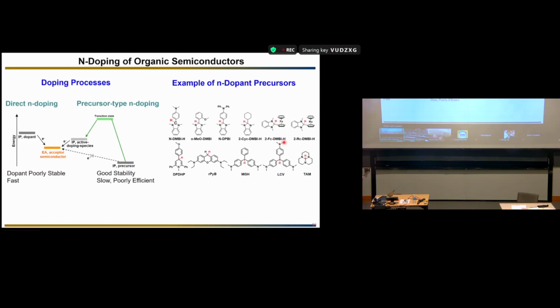But what you do is some chemistry on this molecule to convert it to a species which can then donate the electron. So this process is energetically demanding. So you have a problem of the doping itself, but you also have to solve the problem of converting the precursor of the dopant into the active species of the dopant which transfers the electron. Since this process is difficult, one question we ask ourselves is, can we use a catalyst which helps this chemistry? And it's something that works well.